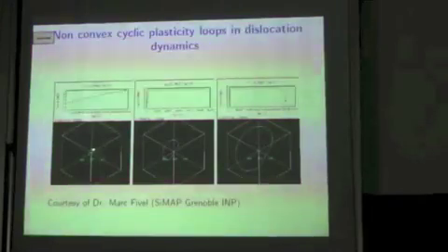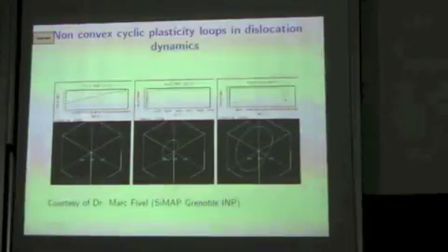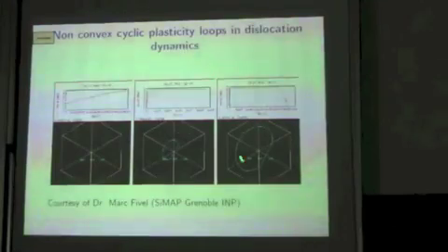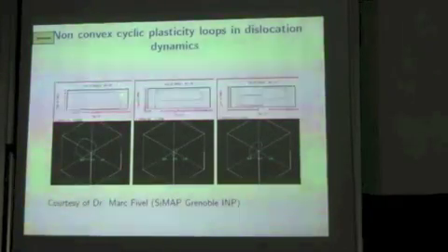You have a dislocation arm which bends and curves, and then the stress increases in shear, and once it's high enough, the Frank-Read source starts working, then it produces loops, and the stress is constant, then you unload. And when you unload, don't look at this, this is simply because there are not enough points here, it's sharp in fact.